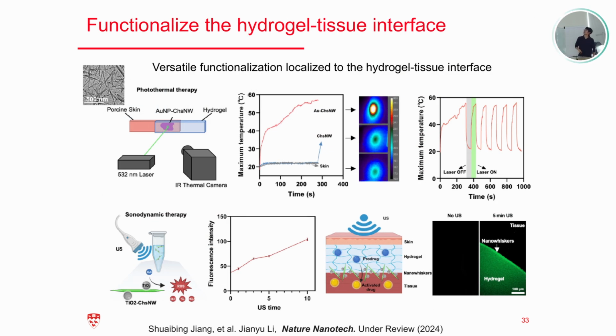In addition to that, I'm sure a lot of experts here know we can also do a lot of things with this nanoparticle, right? We can functionalize it for different functions. I just want to show you the advantage of this strategy is that these nanoparticles are really located at the interface. We can really locate the functionalization to the interface at the hydrogel and tissue surface. So here is just a proof of concept.